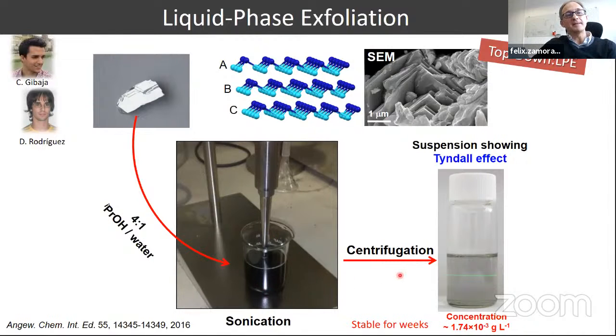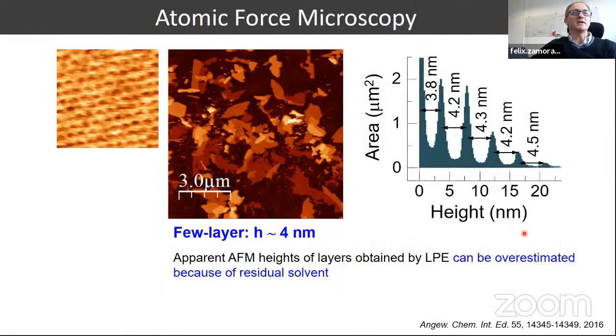In order to get a more homogeneous distribution of the material, we submit this initial suspension to centrifugation. And we end up with this nice suspension, or even we can call it a colloid, because it was stable for weeks without showing any kind of material aggregation. The suspension showed the Tyndall effect, as expected. But if we check the concentration, which is 10 to the minus 3 grams per liter, it was not very high.